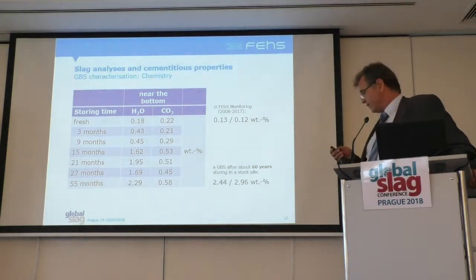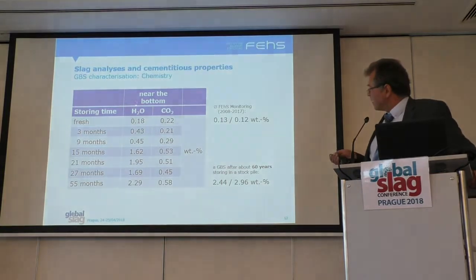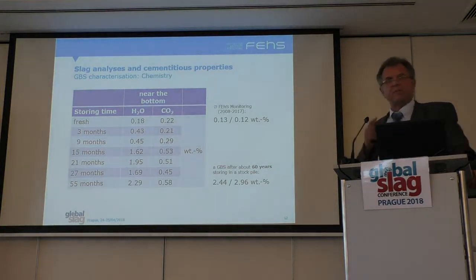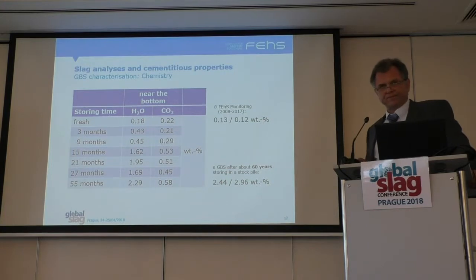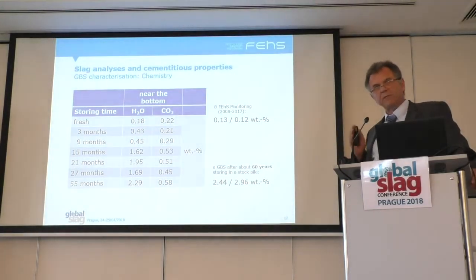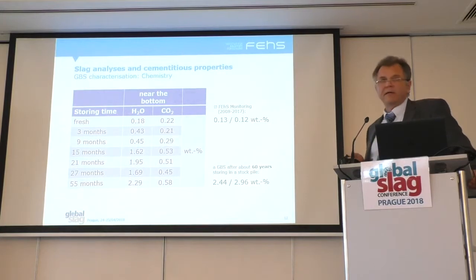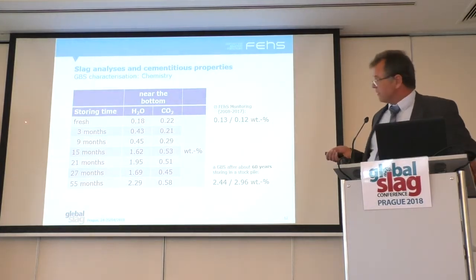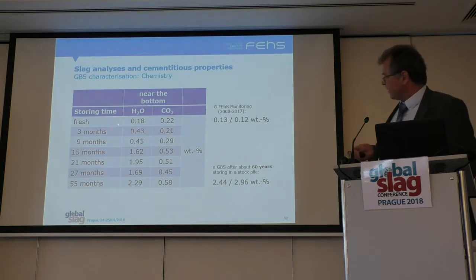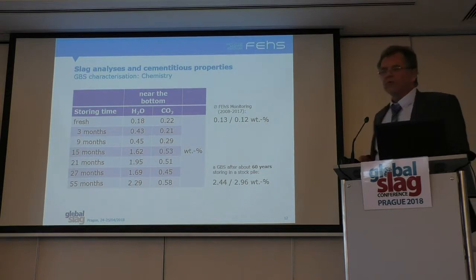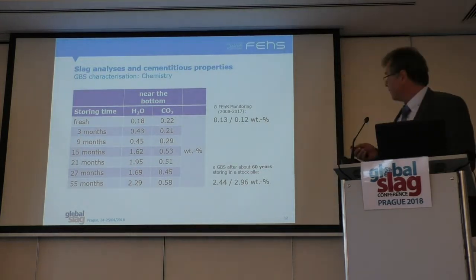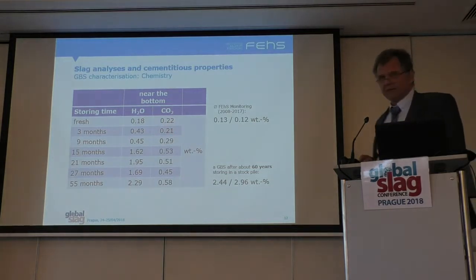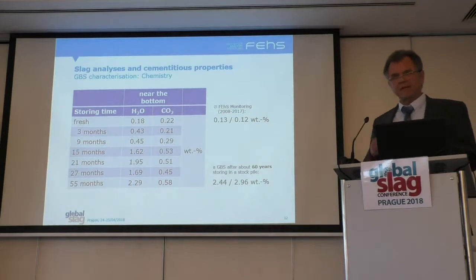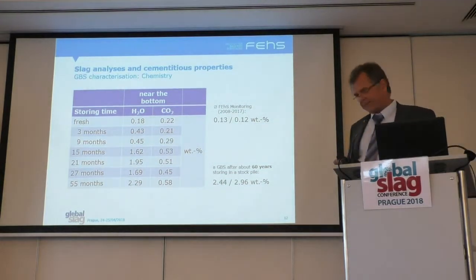But what changed, and that's very interesting, is the content of chemical bound water and CO2. So not the moisture, but chemical bound water in hydration phases. And you see, starting from a low value, during the storing time the value for water increased to 2.3%. It was followed by an increase of the CO2 content, because the pre-hydration products carbonate following the time, and therefore